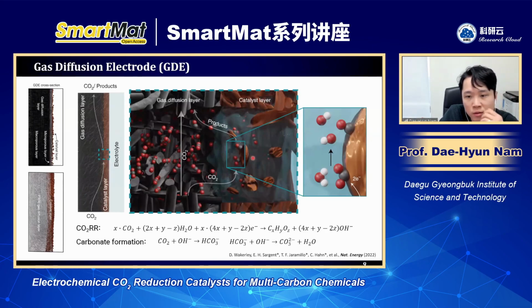So in the GDE, we can supply CO2 from the backside, and at the surface there is liquid electrolyte facing. So we have a three-phase boundary in this GDE, with the solid-state catalyst, the gas phase CO2, and the liquid phase electrolyte. This we call the three-phase boundary. So CO2R can also occur at the surface of this boundary.